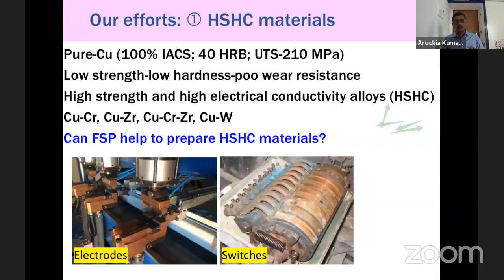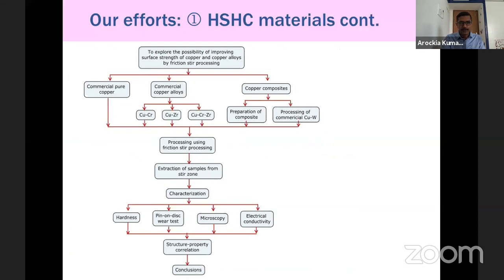So what is the remedy now? Is it possible to develop a high strength, high conductivity material through FSP? That's what we have explored in our work. We chose pure copper and processed it through FSP. We studied its mechanical property and electrical conductivity. And we chose some commercially available copper alloys, which I have listed here: copper chromium, copper zirconium, copper chromium zirconium. All these alloys exhibit 70 to 80% IACS conductivity. So is it possible to improve the strength of these alloys without deteriorating their electrical conductivity?